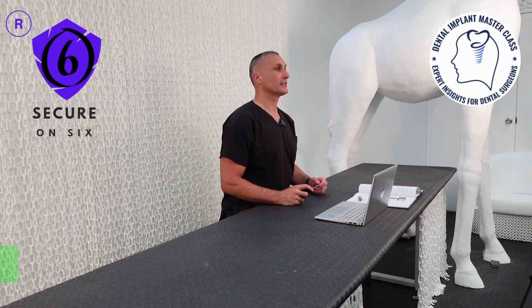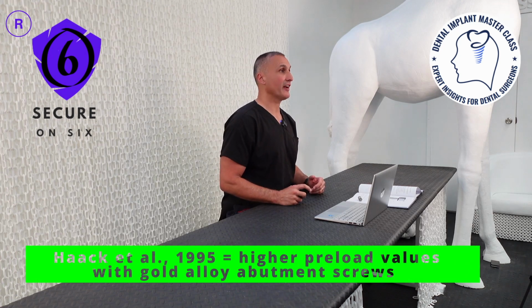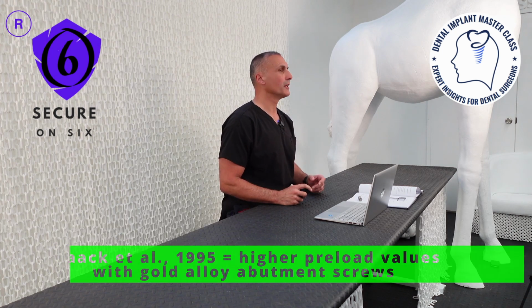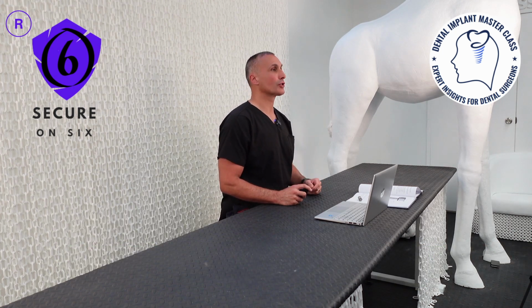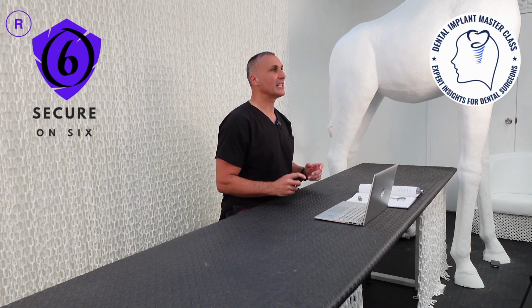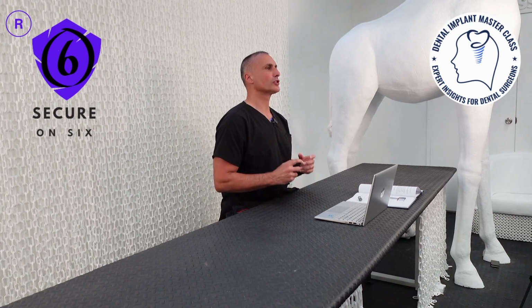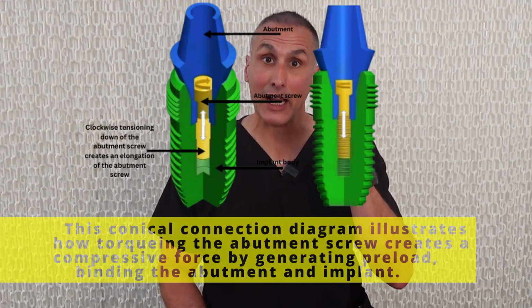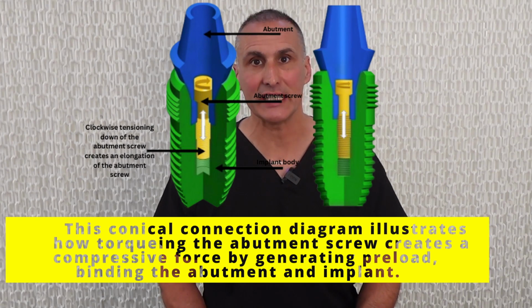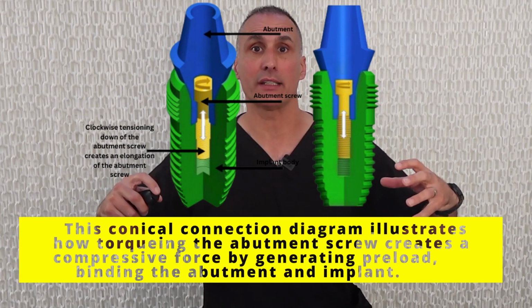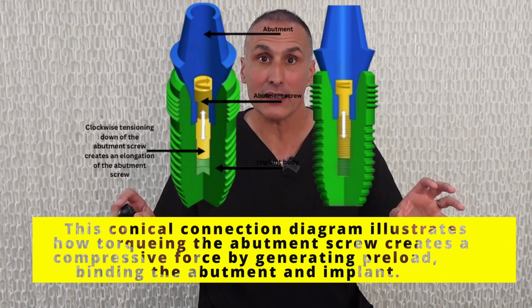Different implant systems from various manufacturers recommend specific torque values for their screws. The efficiency of a material in converting torque to preload has been described by Tan and Nicholls in 2001. Haack et al. in 1995 reported higher preload values with gold alloy abutment screws. Preload is introduced into the screw during the tightening process and serves to keep the screw threads securely fastened to the screw's mating components. This generates a clamping force between the screw head and the seat, causing the screw to elongate and create tension in the flanks and the threads.